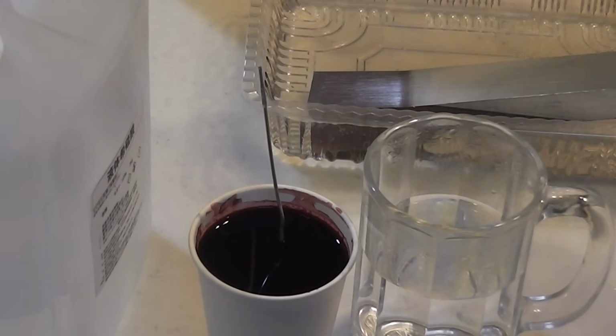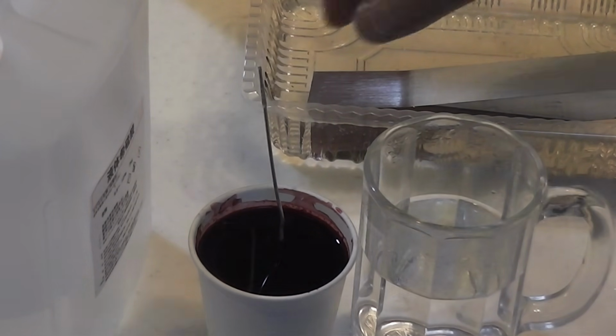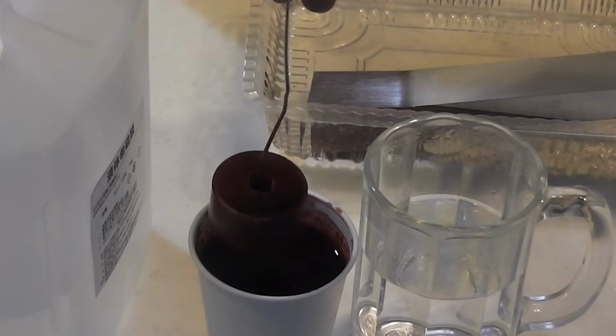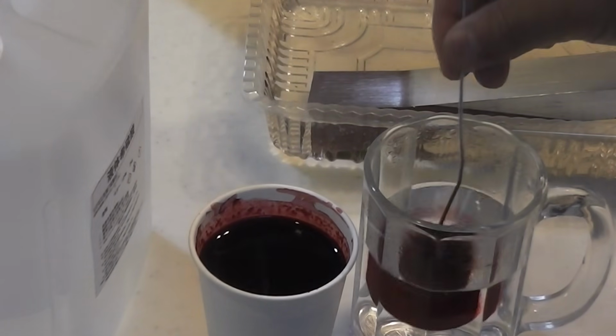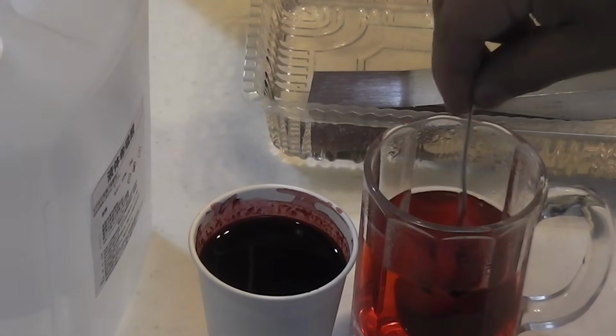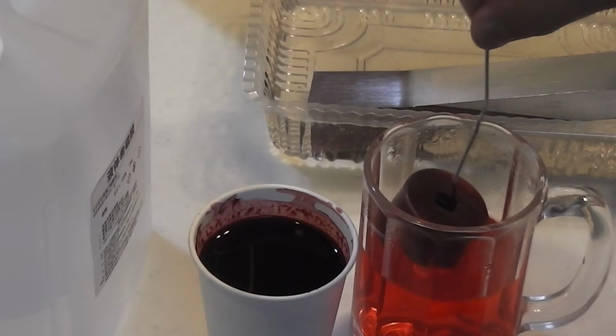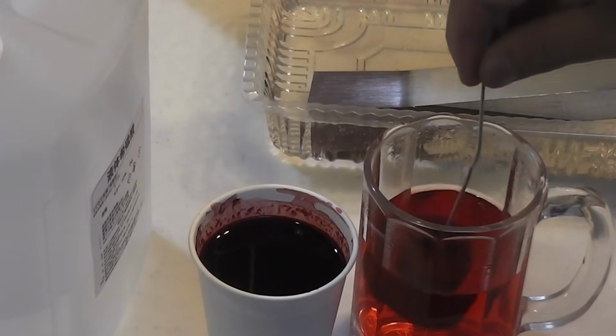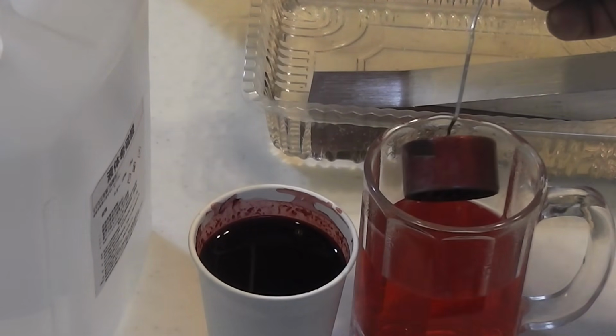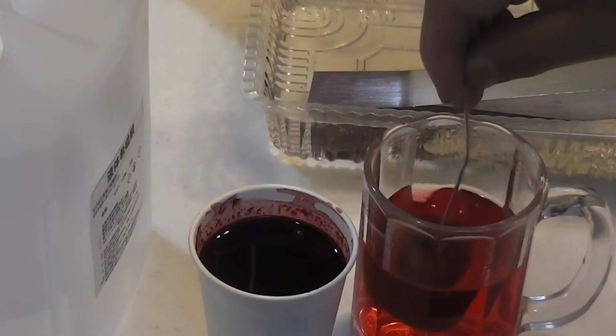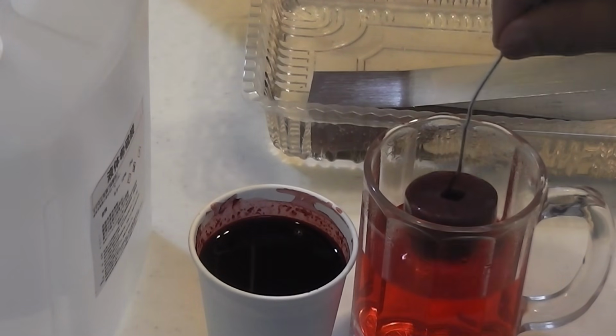To finish the process, the pores must be sealed. The part is placed into hot water. The heat hydrates the aluminium oxide, causing it to expand slightly and close the microscopic pores. As those pores close, the dye becomes permanently trapped inside the oxide layer. This final step greatly improves both corrosion resistance and color durability.